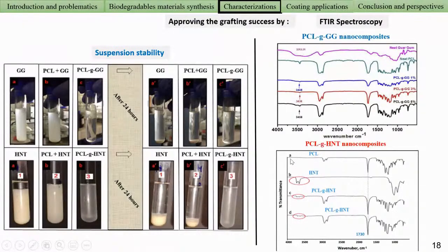As you can see here, we have the IR spectrum of polycaprolactone, halloysite nanotubes, that one is halloysite nanotubes before purification, and here after purification. And we can see, even with halloysite nanotubes or guar-gum, we have the same bonds. We have a carbonyl group between 1700 to 1750, and we have OH groups on the surface. That's indicating that we really grafted the polymer on the surface of the fillers.